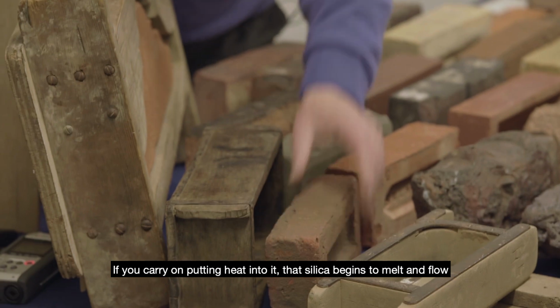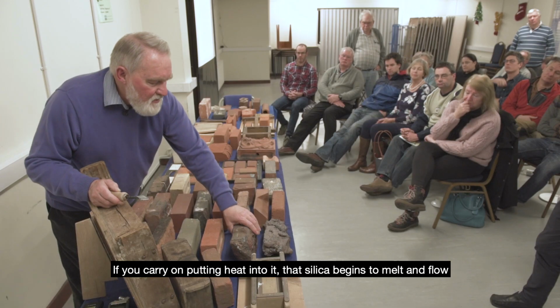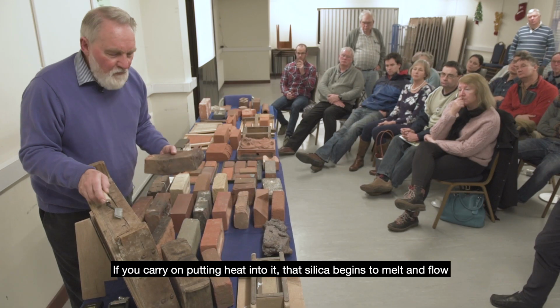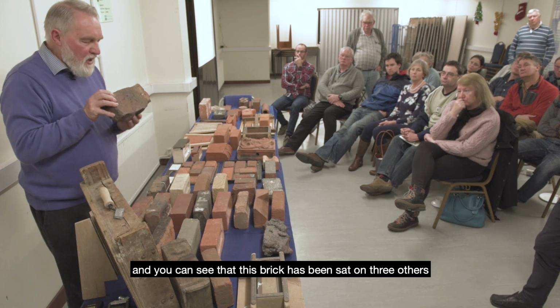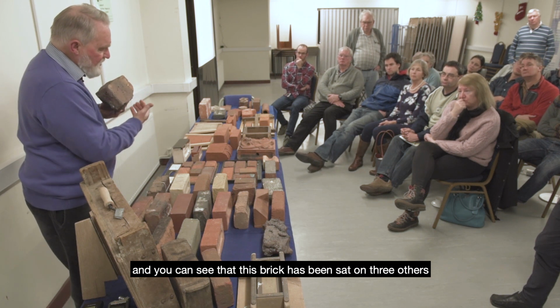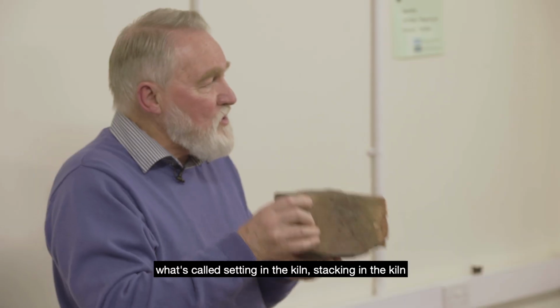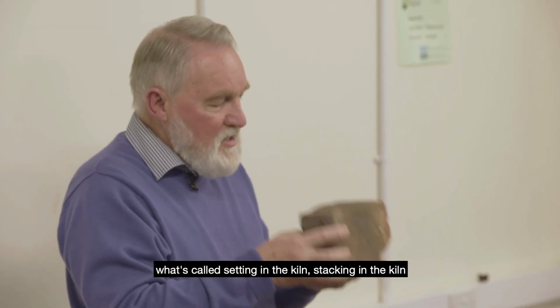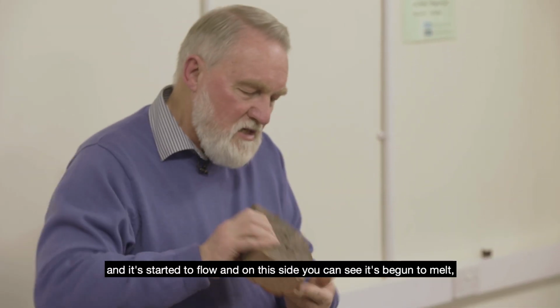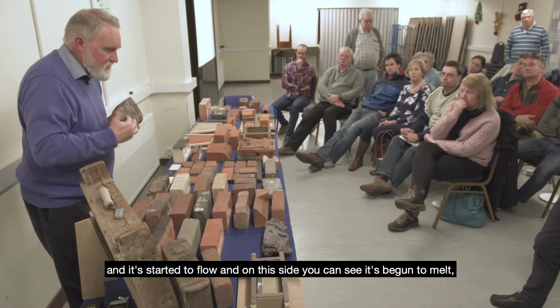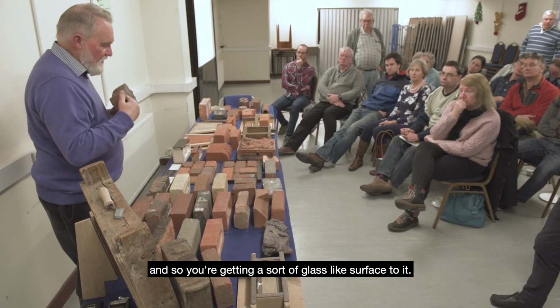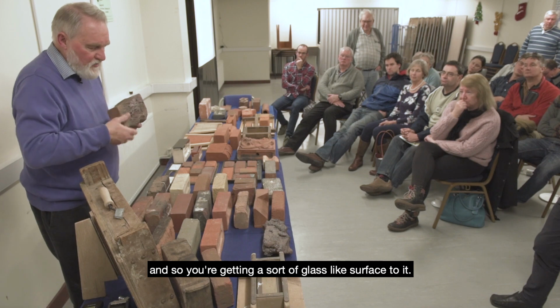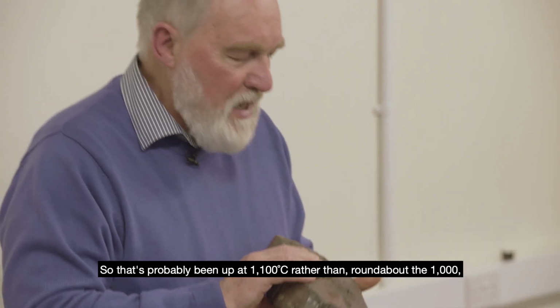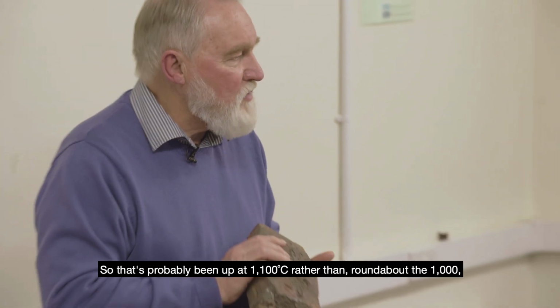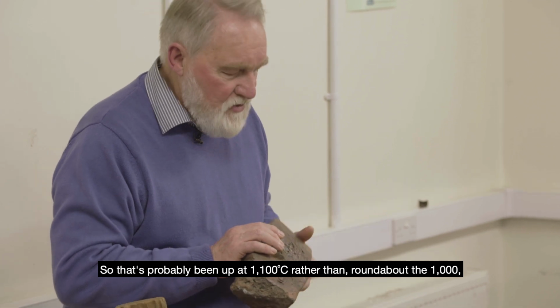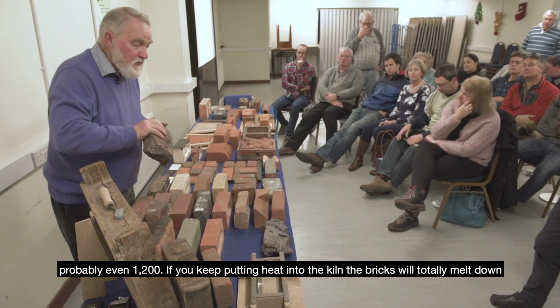If you carry on putting heat into it, that silica begins to melt and flow, and you can see that this brick has been sat on 3 others, the way it's what's called stacking in the kiln, and it started to flow. On this side you can see it's begun to melt, and so you're getting a glass-like surface to it. And so that's probably been up at about 1,100 degrees rather than round about the 1,000, probably even 1,200.